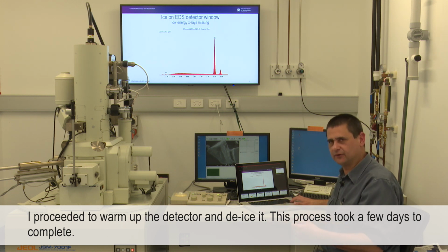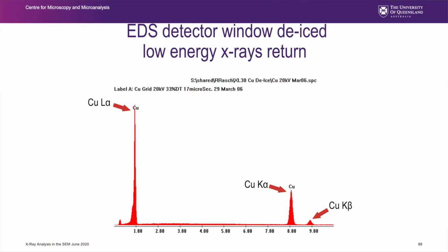I then proceeded to warm up my detector and de-ice it. This is an old liquid nitrogen detector. That actually took a few days to gently do it. And then the same detector, a little bit later, freshly de-iced. And you can now see the copper L peak is enormous compared to the K peak.